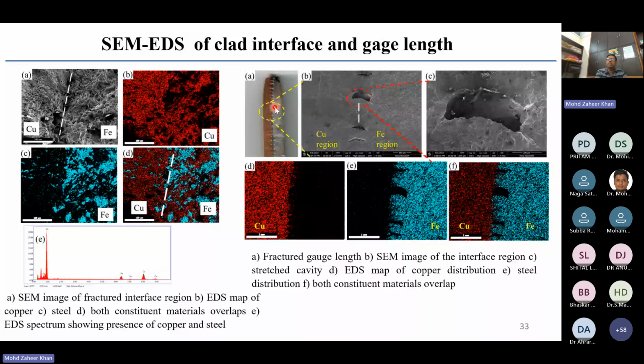These types of perpendicular voids are created, and under the SEM also we can see these voids that are present, and the material has not separated out. When we performed EDS of it, we found that this region was completely copper, and this was steel. So no intermixing has taken place, and these voids that have been created are partly on the copper side and partly on the mild steel side. So very good interlocking of these two has taken place, which can be proved.